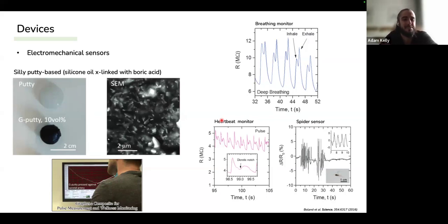On the electromechanical sensors, we take our dispersion, from the same one that we have in the sensors, the ones I just showed you, we mix it in with a polymer like putty, and then when we print it, what we find is we have extremely sensitive strain sensors. So this is Connor Boland here. He held a network like this up to his neck, and he was able to monitor his breathing, inhalation, exhalation. He also was able to monitor heartbeat. He was able to discriminate the dicrotic notch on the heartbeat, and he found a spider in the lab, and he had the spider walk across one of these sensors, and he was able to detect the spider's footprints.